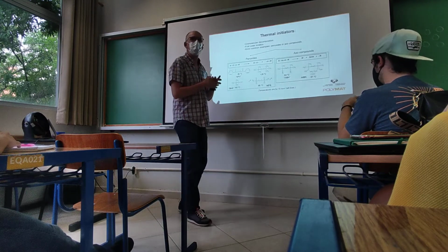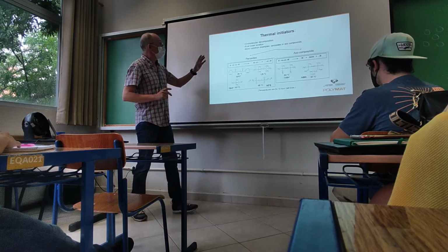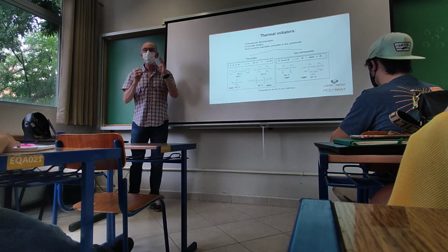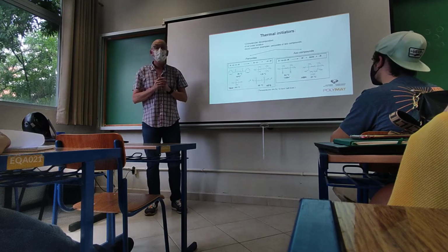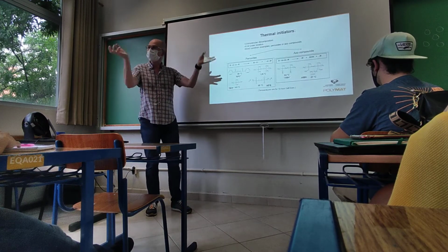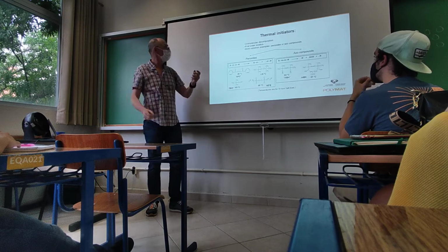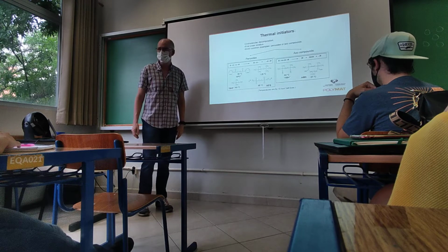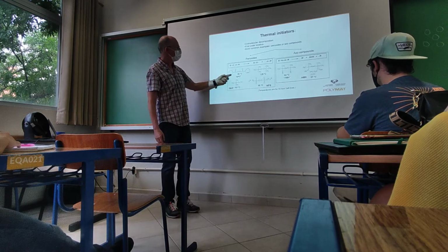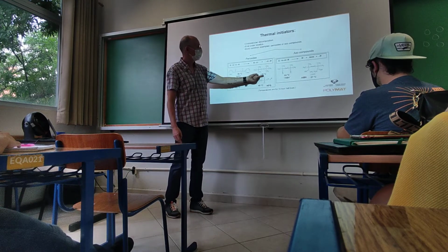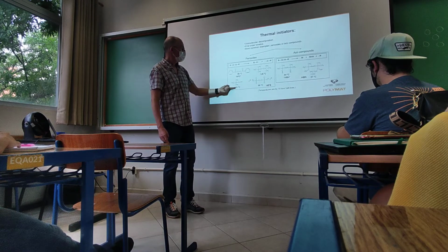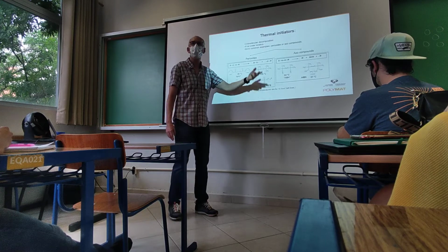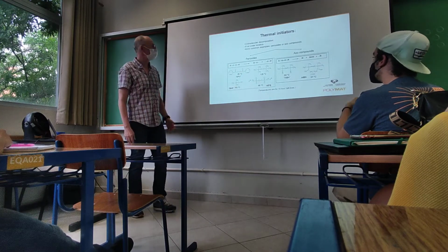The initiators that are used in emulsion polymerization. Most of the initiators are thermal initiators, which means that they decompose with temperature. So at a certain temperature, the initiator will decompose and create radicals. Normally, peroxides and azo compounds are used. Peroxides can be benzoyl peroxide, tert-butyl peroxide, tert-butyl hydroperoxide, or persulfates, potassium, ammonium, sodium, which can be used in different systems.